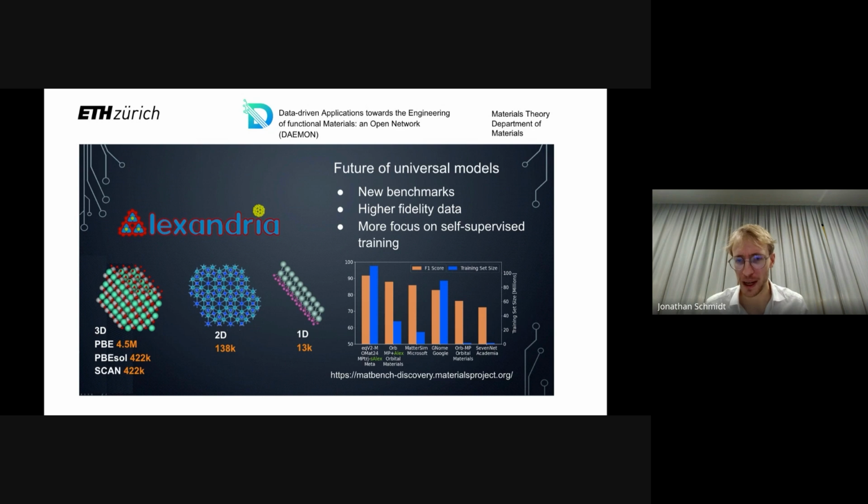I would not recommend using the distance to the convex hull on more than 5 element systems in general, just because entropy plays such a large role that the knowledge of the distance to the convex hull is not sufficient, let's say. Maybe there were a few compounds with more than 5 elements in the training data, but we have only ever done predictions for quaternary compounds, because everything beyond that gets too much into the entropy regime. And already for quaternary compounds, this order is important. Nice.